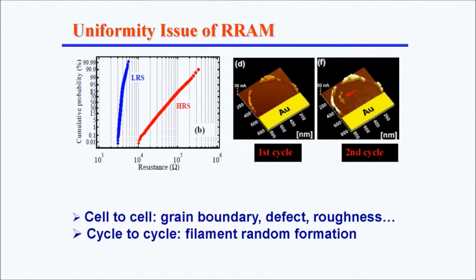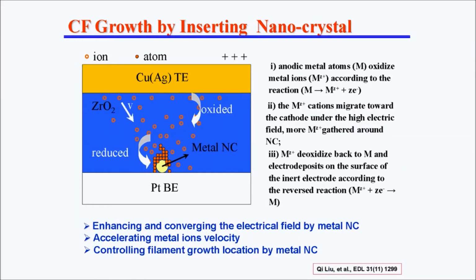So why does this cause the larger distributions? We try to understand. We can clearly see that's because the filament forming and rupture process is a random process. That's a big problem. So based on this knowledge, if we can control the filament forming and rupture process, that means we can get a very tight distribution for this device.